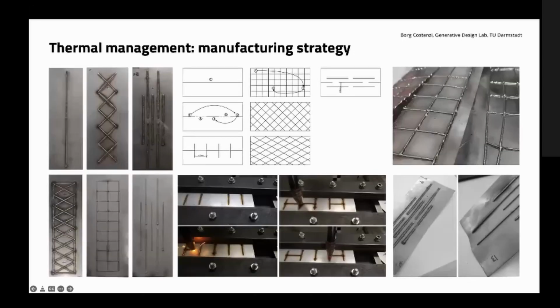And also welding onto thin sheets is an extremely challenging process because, as I said earlier, with this wire arc additive manufacturing process, the thermal management is an issue. So instead of printing a continuous line, as shown in this picture, we might want to break up the lines that we're printing into individual segments, print 1, print 2, print 3, and then 4 and 5 to connect it and to allow for the heat that we bring into the sample to dissipate. Similar with ribs that we print in different locations, we have to break up the structure that we add on top into individual pieces in order to allow for the heat to dissipate.